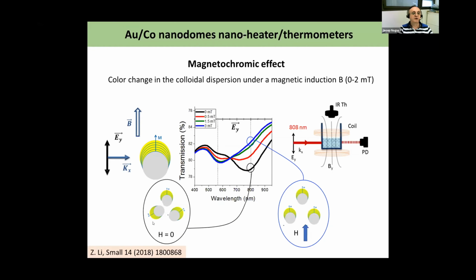Because at zero field, the nanoparticles are randomly distributed, but when we apply the field, all the particles align to the field. Since these particles have asymmetric optical properties, when they are random, the absorption is very different than when they are aligned. That's why the transmission changes very much with the applied field. So now we use this idea for sensing.